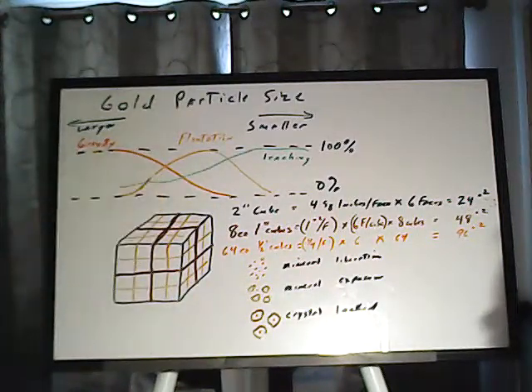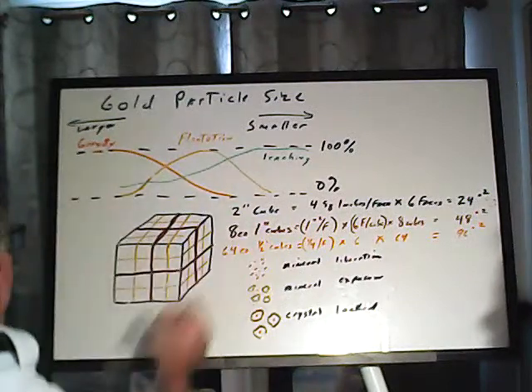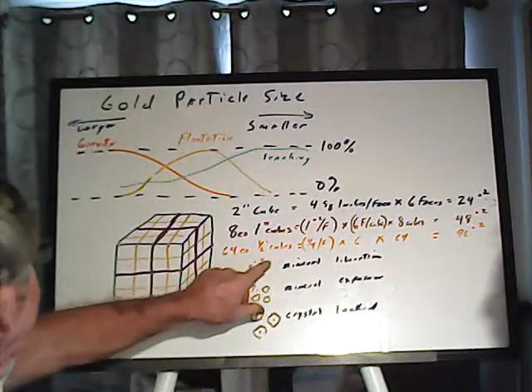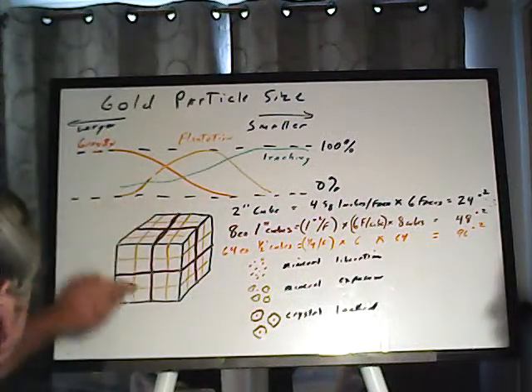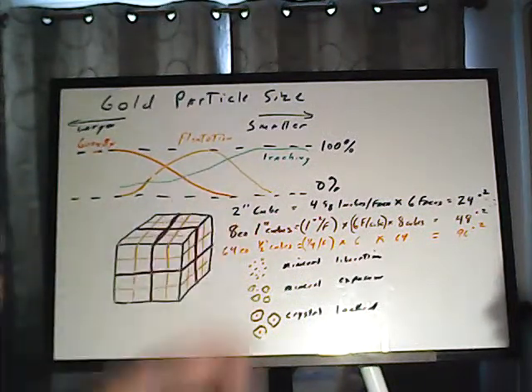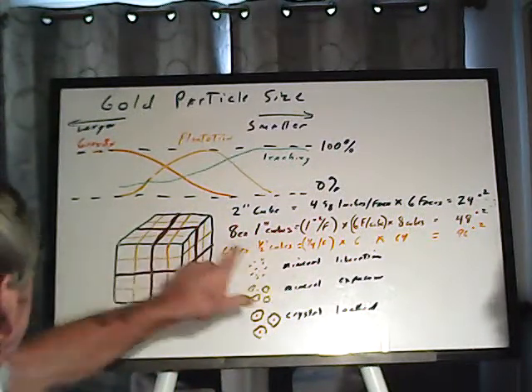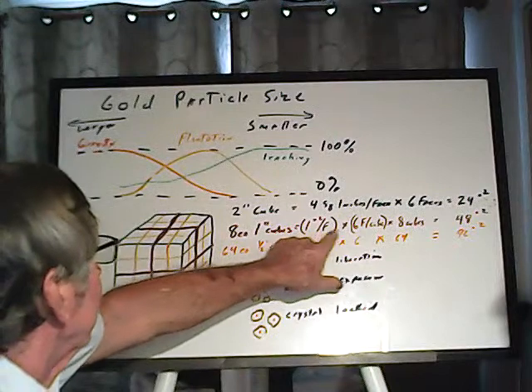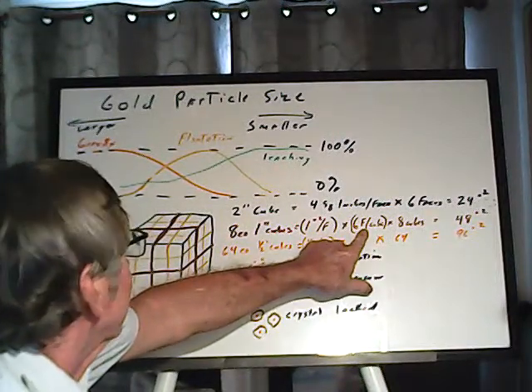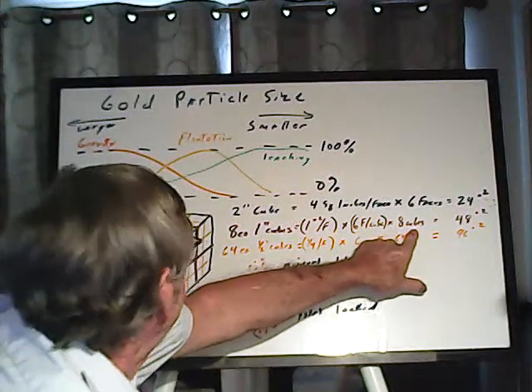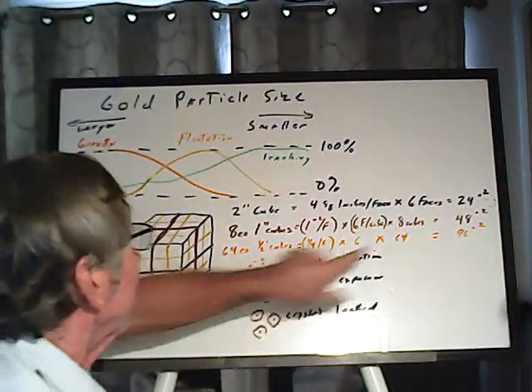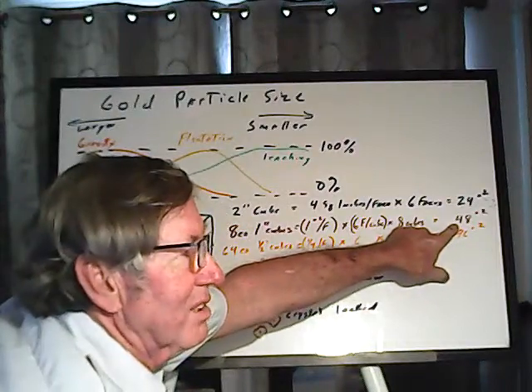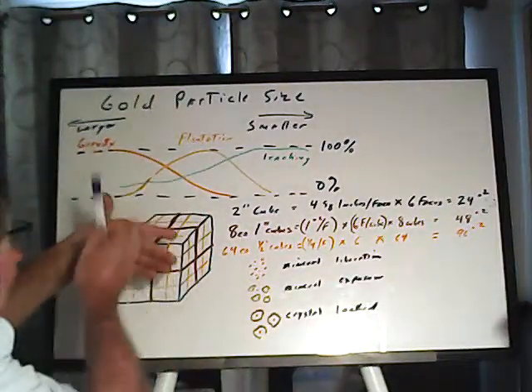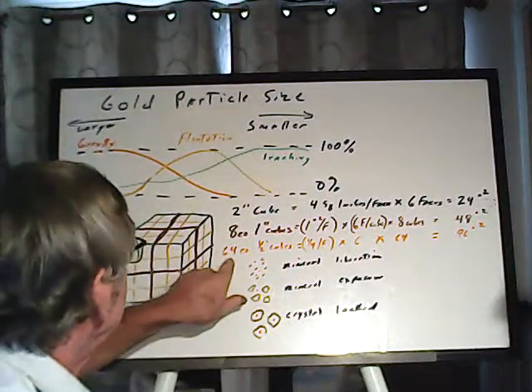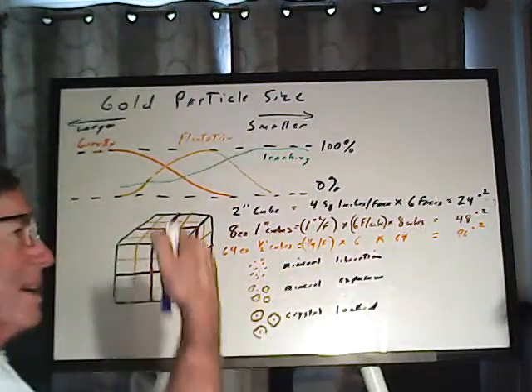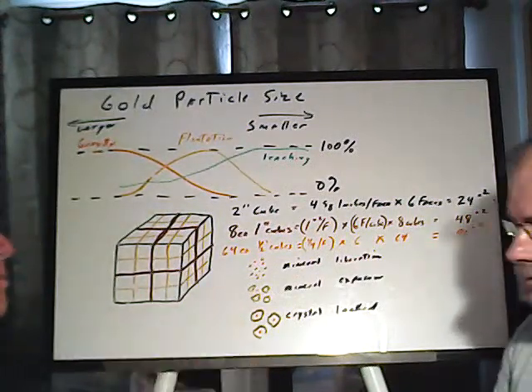Now if you take the exact same amount of material and cut it again into 1-inch cubes, you now have 8 cubes. 1, 2, 3, 4, 5, 6, 7, 8. Each one 1 inch on a side. So it's 1 square inch per face times 6 faces. That'd be 6 square inches per cube times 8 cubes, which gives you 48 square inches of surface area. So by cutting it in half, you double the surface area. If you do it again, you get the same thing. Every time you cut it in half, it's half the size, you double the surface area.